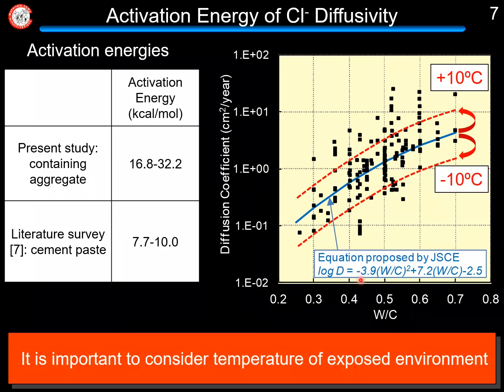From this graph, it is observed that the scattering of chloride ion diffusivity in the literature data seems to be explained by temperature effect. Therefore, it can be considered that the temperature profile is one of the most important factors when we check the diffusion coefficient of chloride ion in the design stage.